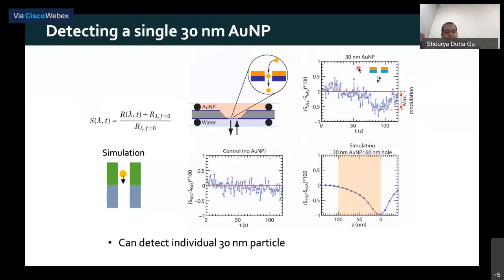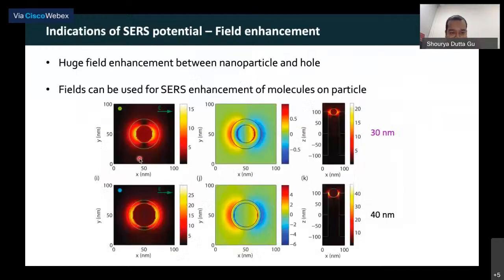So what we're able to do here is measure the particle as it is going through this single channel that we have. Right now, you might ask me, how is this connected to SERS? If you look at the calculation shown here, if you place this particle, the center circular region, in the hole shown by the outer green circle, the fields are very enhanced. It is enhanced by a factor of 15 as compared to when you don't have a particle.